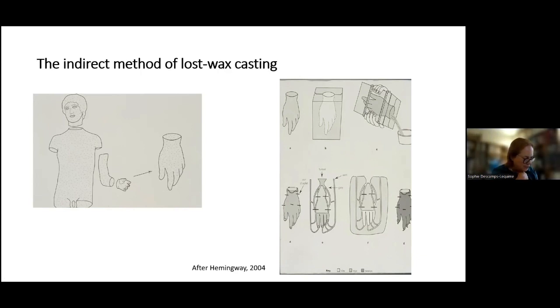Traces of the process used to introduce the wax into the mold can sometimes be seen on the inner wall of the bronze. Brush marks, drips. On this particular example, the wax was poured into the master mold, to which a back and forth movement was applied, and the excess wax was evacuated. Then a liquid clay core was poured inside the master mold, lined with wax. Then the master mold was removed, and this was done for each separate joining section.